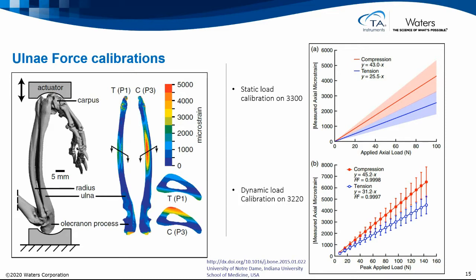And in order to understand that well, we see here some really nice, thorough images and characterization of how much strain do we actually get and where is that strain in the ulna bone as a function of force. So the plots on the right are essentially a calibration curve of sorts where they look at, for a given amount of axial force applied to the joint, to that forearm, in the ulna bone, you've got compression strain in this case, and tension strain. And looking at over multiple animals, characterizing then how much strain do you get when you apply a given amount of force. So what you'll see later is they then vary the force for different specimens and then look at how that bone is formed at those various levels of force.